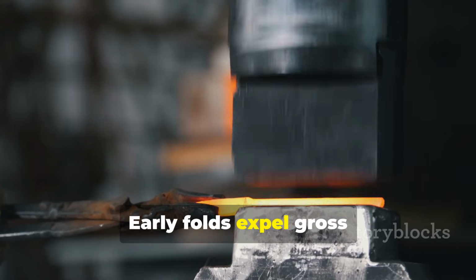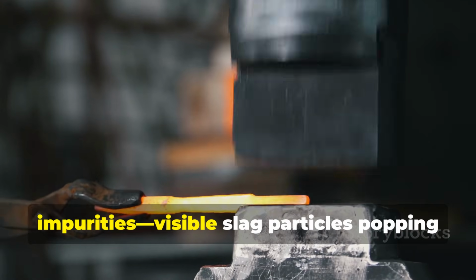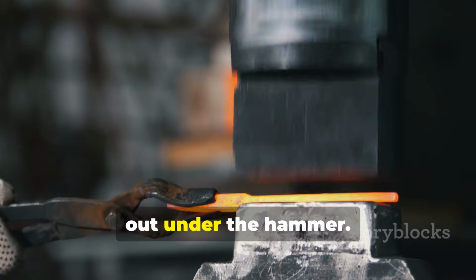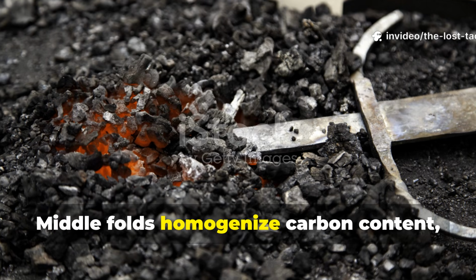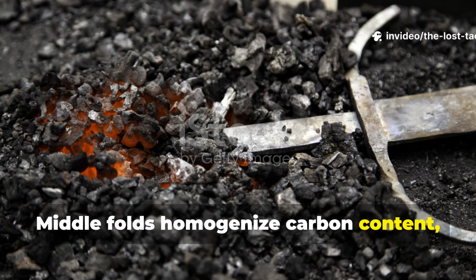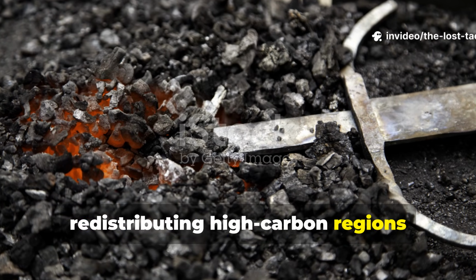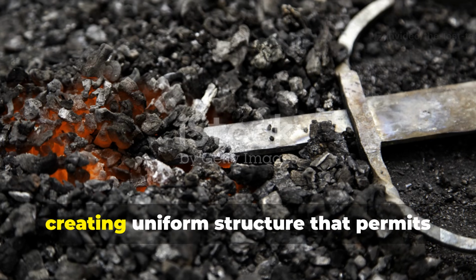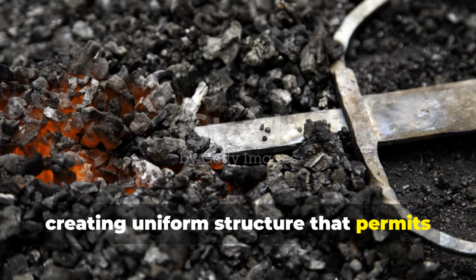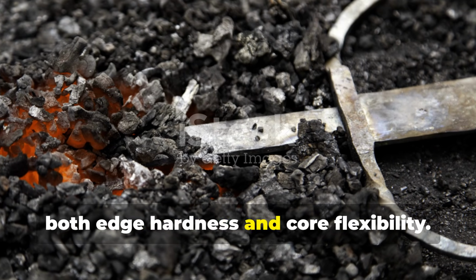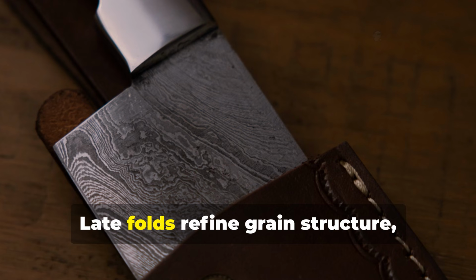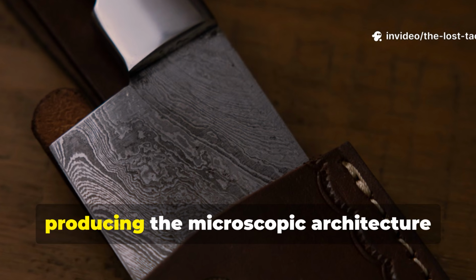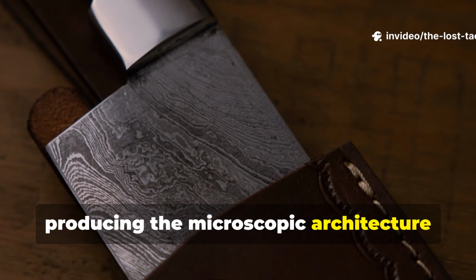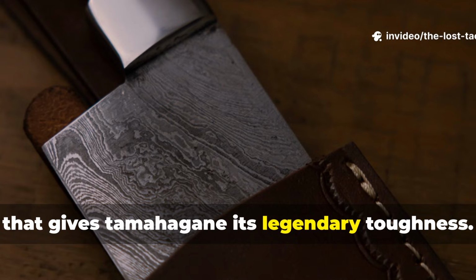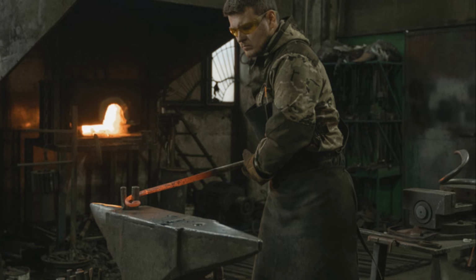Early folds expel gross impurities, visible slag particles popping out under the hammer. Middle folds homogenize carbon content, redistributing high-carbon regions throughout lower-carbon areas, creating uniform structure that permits both edge hardness and core flexibility. Late folds refine grain structure, producing the microscopic architecture that gives Tamahagane its legendary toughness.